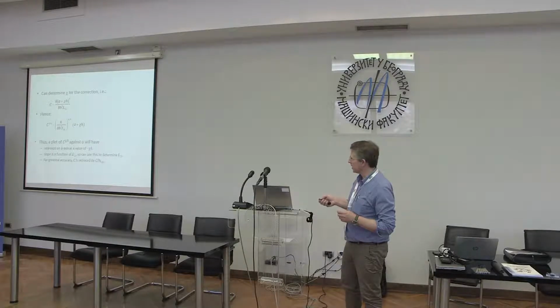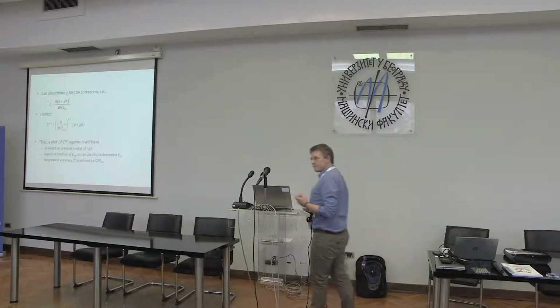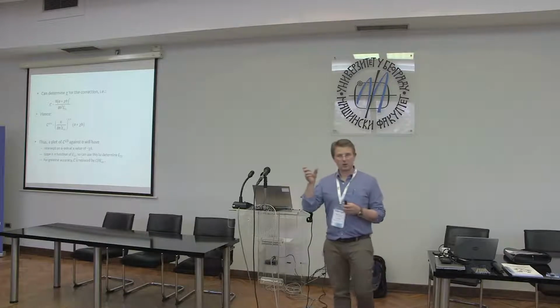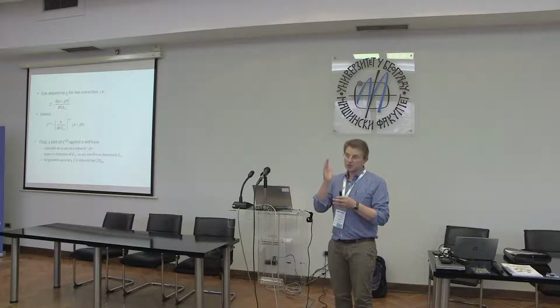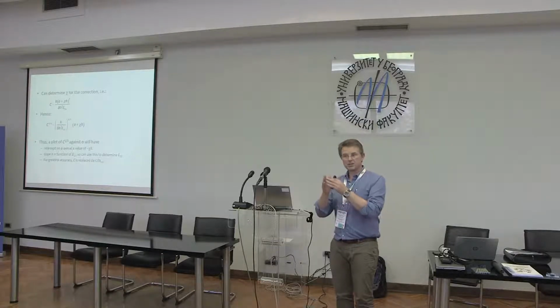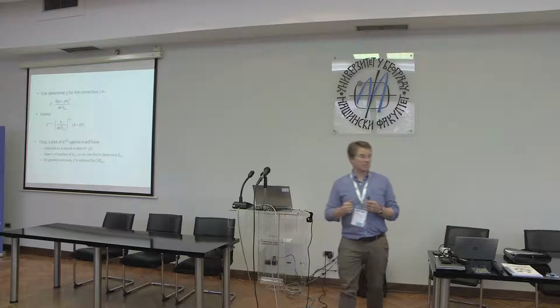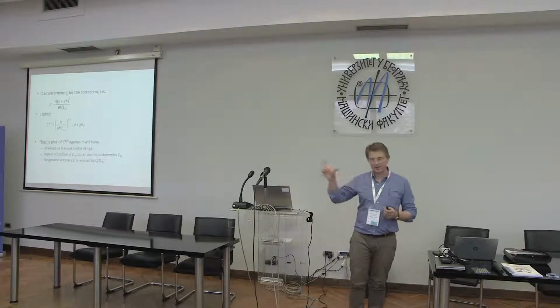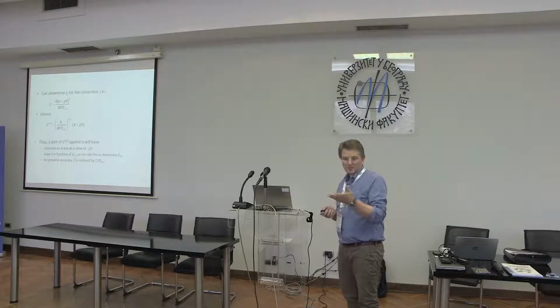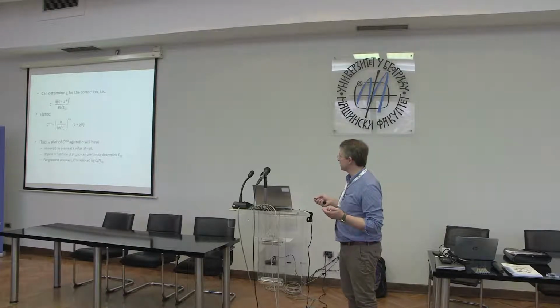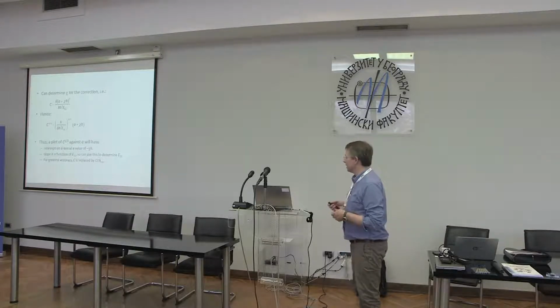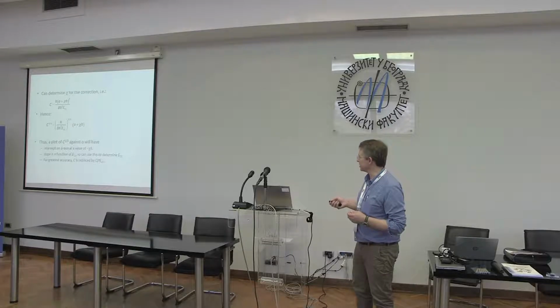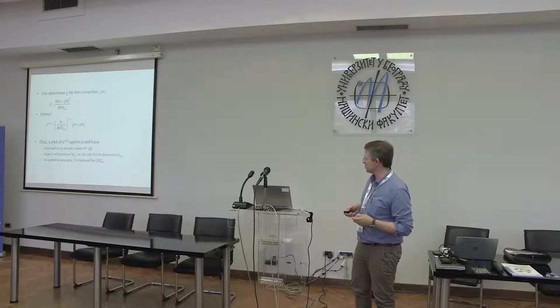So this is the standard compliance equation based upon simple beam theory, modified by a slightly longer crack length. The idea about this slightly longer crack length is that although the condition is not perfectly built in at the crack tip, at a condition a certain distance ahead of the crack tip, it is perfectly built in. So you can make that modification to the analysis. If you can easily determine that, then it's useful. And of course, it is quite easy to determine it because from our experimental data, we can determine the compliance. And what we've effectively done here is we've just linearized that equation with respect to a